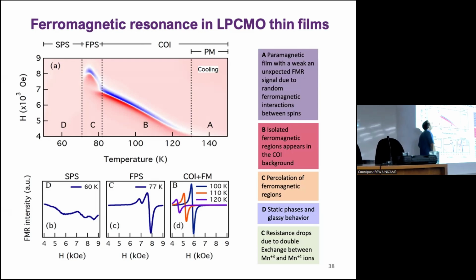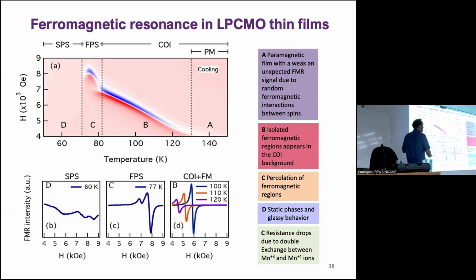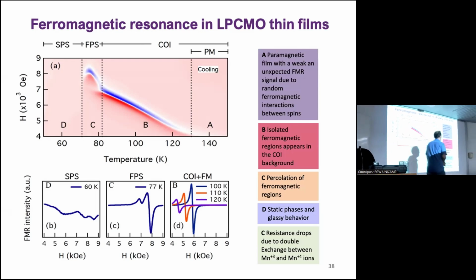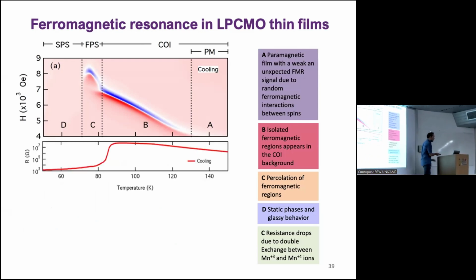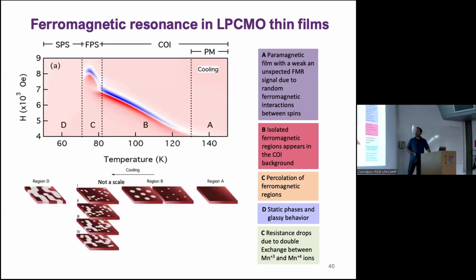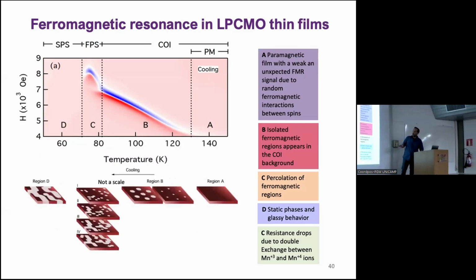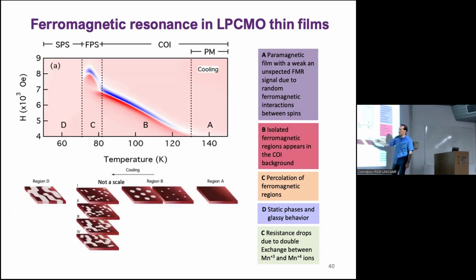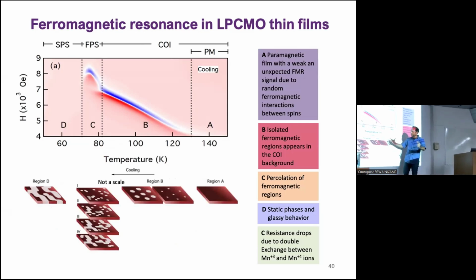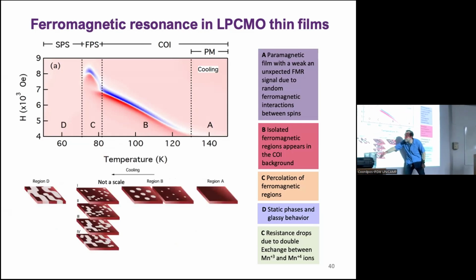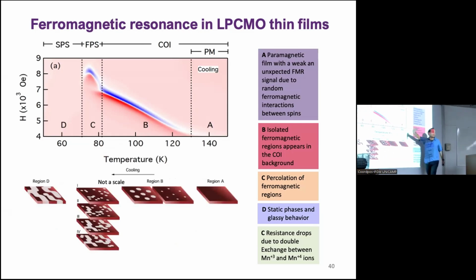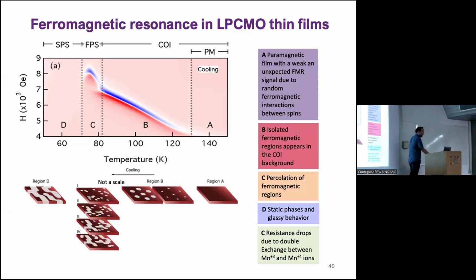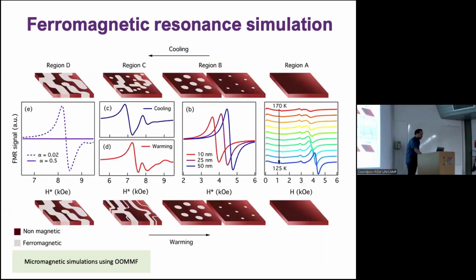Okay? So, what's the idea? We try to explain this somehow, and then this is what we can do. So, basically, if you assume that this is your sample, you have ferromagnetic domains, they grow, they connect, they percolate, they freeze, you can reproduce the entire curve. And I probably will stop with that.